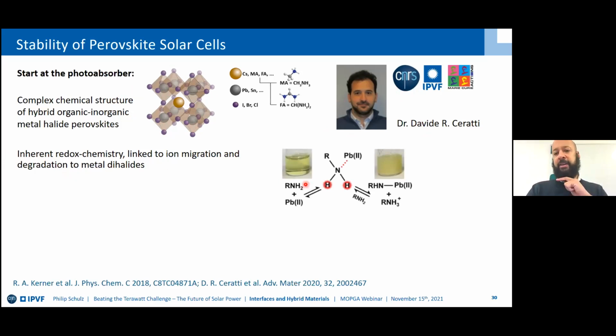And this is what we look at, complex chemical reactions, where we here in a vial mix the different components and see that if we mix amine with divalent lead, we can get the soft lead amine bonds that will then fully form lead amides. That is a very unstable compound, thereby releasing actually also hydrogen.